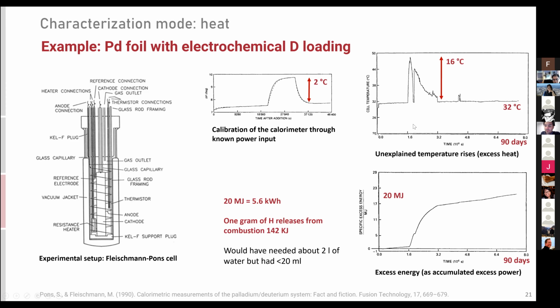If you map the temperature to power, and then you accumulate the power over this period, then you get the total energy measurement. The total amount of energy was 20 megajoules, which is about 5.6 kilowatt hours. 1 gram of hydrogen releases about 142 kilojoules from chemical combustion. So they would have needed about 2 liters of heavy water, but they only had about 20 milliliters. So there was a much larger amount of energy measured than would have been expected from purely chemical effects.